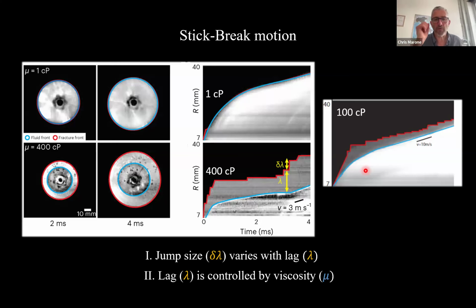Ilya, it's Chris. Sorry, I've got a dumb question. So you have the injection rate constant, and the fluid doesn't show the same jumps, at least at 400 centipoise, as the crack position, but the blue line is not straight either. Is that the pressure building up in the crack? So the injection rate is constant, but it's really, really slow. So during the experiment of 5 milliseconds, there is no fluid injected by the pump.